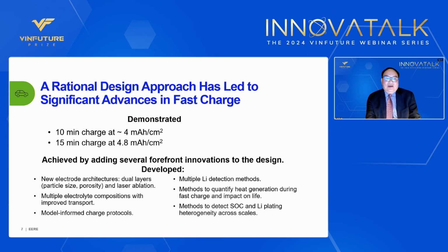So you can achieve several forefront innovations to design by new electrode architectures using dual layers and laser ablations. You use multiple electrolyte compositions with improved transport. You can develop multiple lithium detection methods to quantify heat generation during fast charge and its impact on life, and a method to detect SOC and lithium plating across all scales.